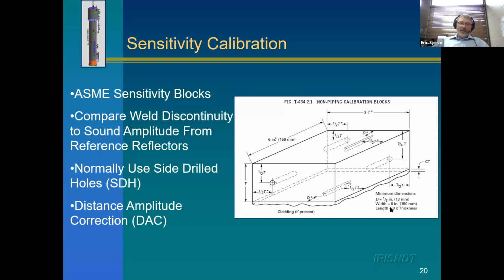The second part is the sensitivity. So once we've calibrated the transducer and we know the y equals mx plus b, or we know the velocity and the delays, we have to make sure we have the right sensitivity, because we don't want to do an inspection and end up calling very small defects because they're not a problem for fitness for service. We also don't want to miss very big defects. So we need to do sensitivity calibration.